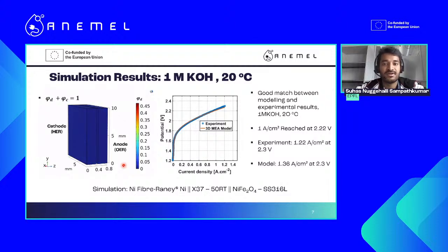Here are the first results that we procured. The blue curve shows the experimental data, and the red one is the model representing the experimental data. You had a fairly good, reasonable overlap. The materials chosen to validate experimentally were Raney nickel or nickel felt, a membrane from Dioxide Materials, X3750RT, and nickel iron oxide on stainless steel.